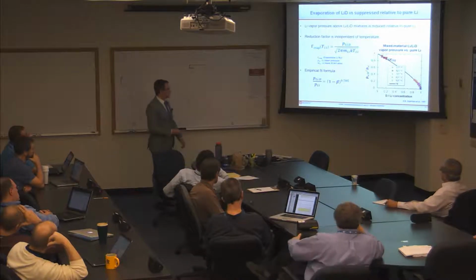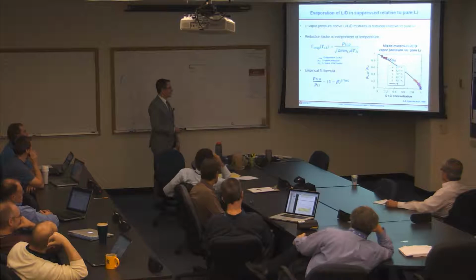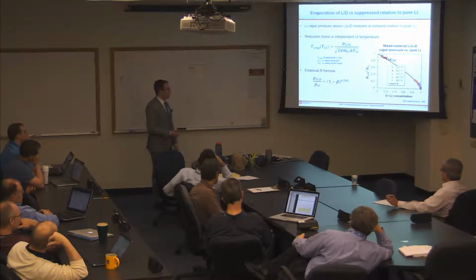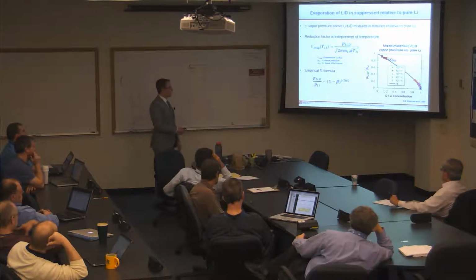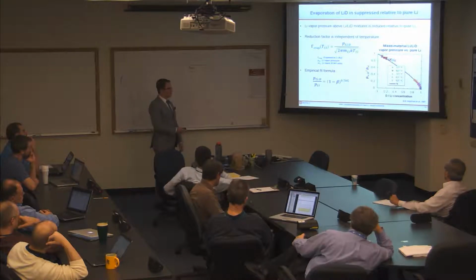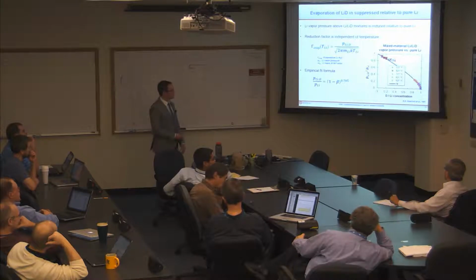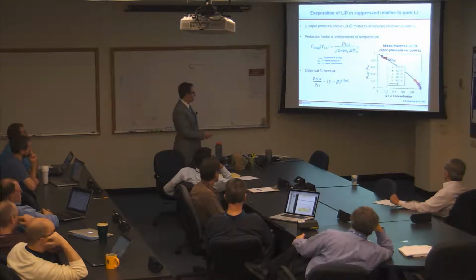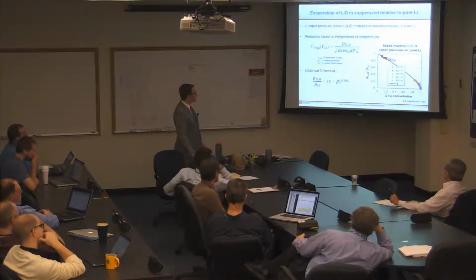So what I did is fit this empirical formula, which is just 1 minus beta to some power, and the fit is shown here in black. Basically this establishes the very logical boundary condition that there should be no reduction in the evaporation at beta equals 0. I assume that the experiments go up to lithium concentrations of about 0.999-ish, 0.998 maybe, and it really seems like it's going to 0, so that was the motivation for this particular power law formulation. And so this 0.705 is a fit parameter.